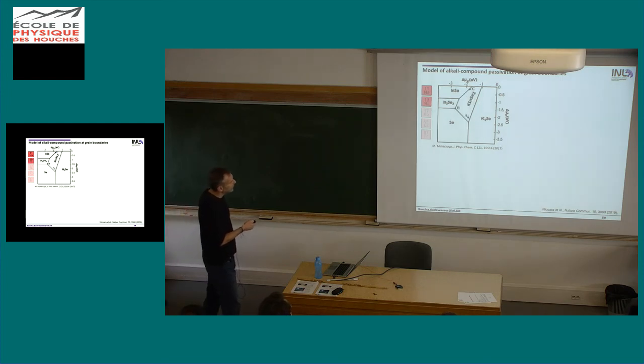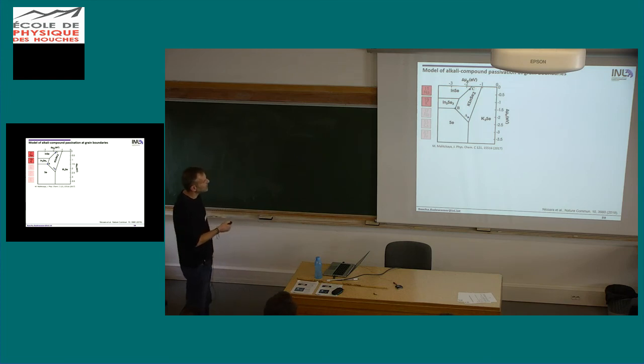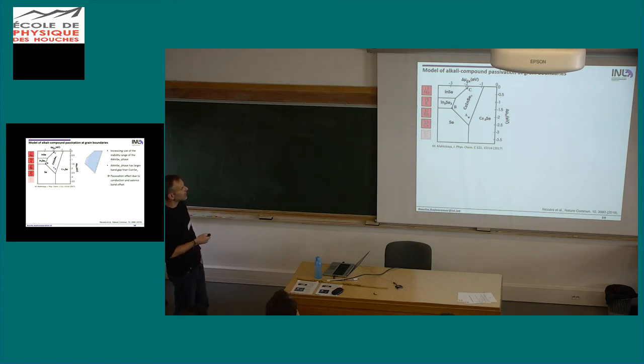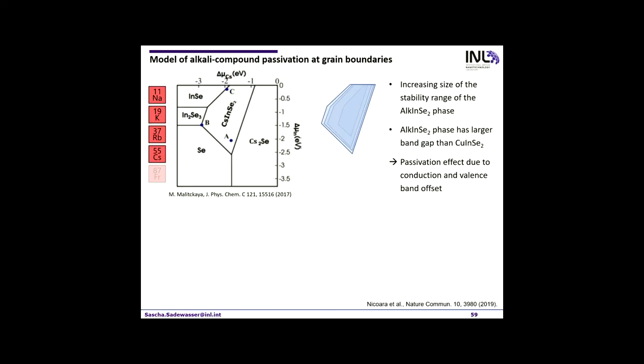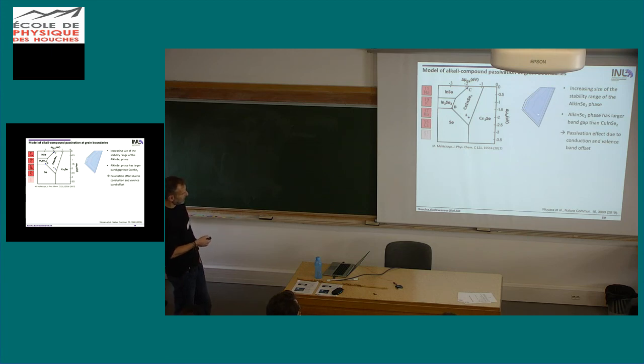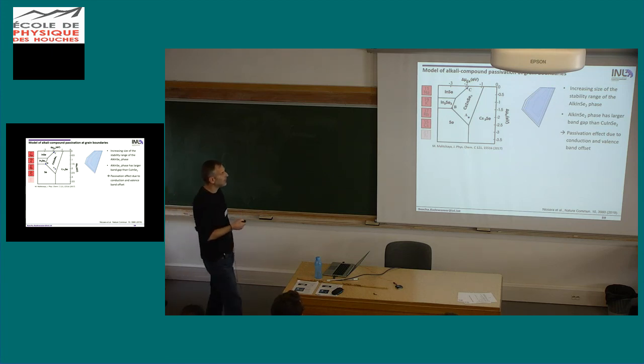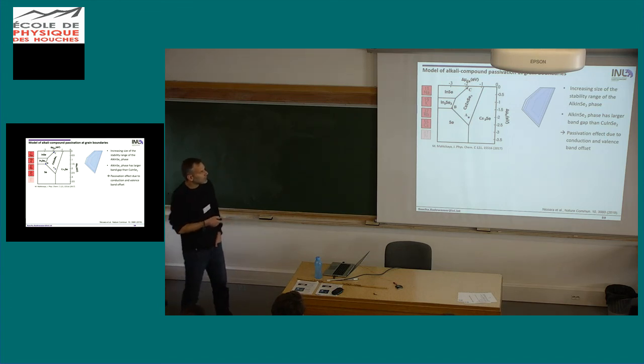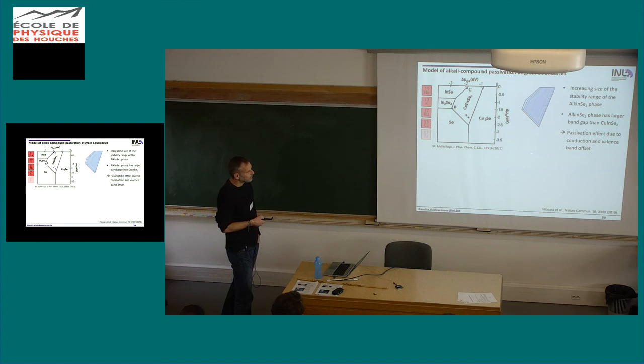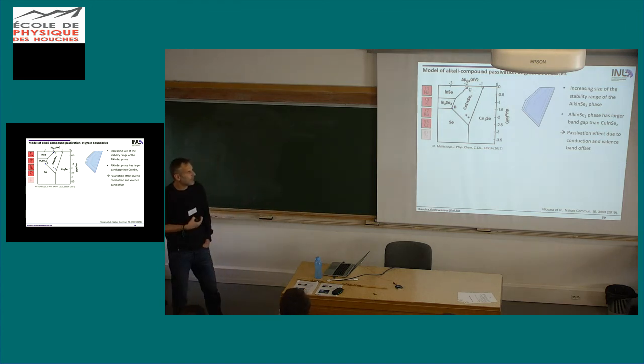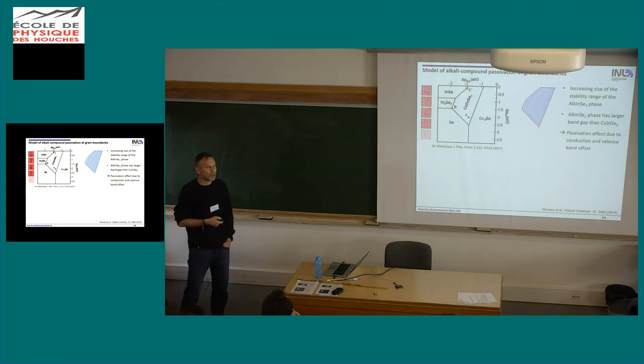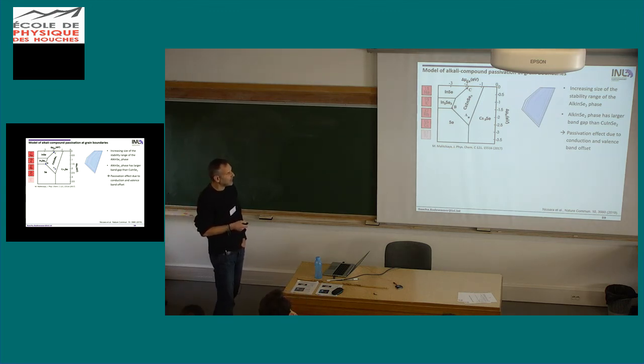And if we now go to potassium indium, we see that the stability range is actually larger. The axes don't change here. So rubidium is even larger and cesium is even larger. So if I plot these four differences here, we can see that the heavier the alkali element, the more range of stability I get for this phase. So that means, depending on where my chemical potentials are, the alkali indium selenide phase gets more and more stable the heavier my alkali element is.